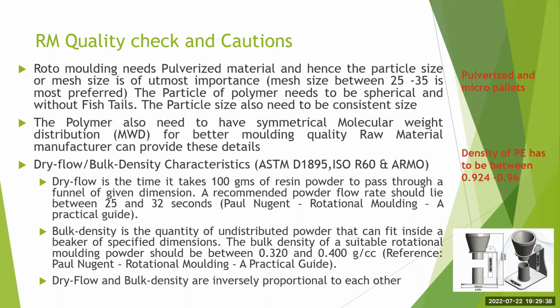25-35 mesh is the most preferred. And we need to look very cautiously here because the particle size has to be spherical and without fishtails. Now, when fishtails are created, if your pulverizing machine is not proper, if the blades are worn out, you start getting fishtails. Even when the blades are worn out, the particle size distribution is also disturbed. And you will get a minimum-maximum range and the differentiation is too high.